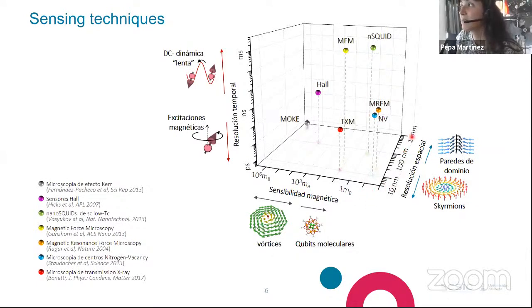Also important is the spatial resolution, because ideally we want to distinguish small regions of magnetization, especially when doing microscopy, but also to distinguish different regions, like for instance the domain walls or vortices or skyrmions, etc. And a third characteristic that is very nice is the time resolution. Magnetic phenomena usually take place in extremely broad ranges of frequencies, from very slow processes, like the slow relaxation of superparamagnetic particles, up to extremely fast processes, like magnetic excitations in domain walls or in spin waves.